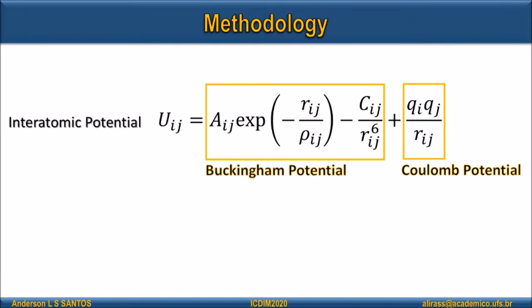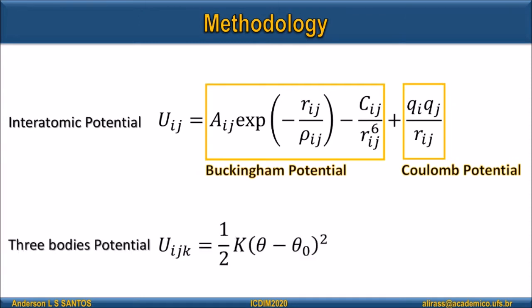Buckingham and Coulomb potentials were used to simulate the interactions of ions in the lattice. These potentials are commonly used to describe ionic and partially ionic solids. We use these kinds of potentials to describe interactions between rare earth ions and oxygen ions. The first equation represents the interatomic potential between two such ions. Additionally, we added three-body potentials to describe strictly the interactions between silicon and oxygen ions.